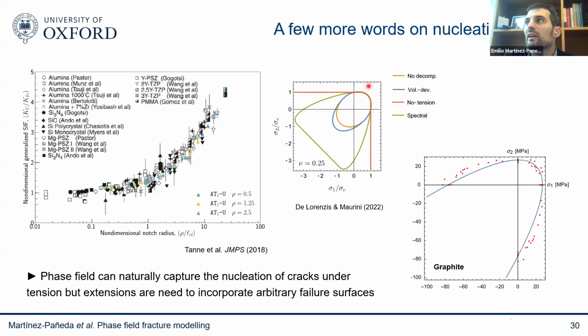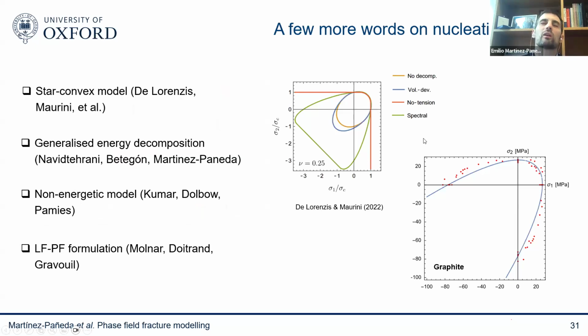With the no-tension split, that is quite used for masonry materials, you get something like this, and also the spectral split. But there are many others, and there's a lot of people working on trying to incorporate any arbitrary failure surface. So you say, now I'm working with granite, with cast iron, with this type of rock. Okay, we have these experimental data points. Let's feed that to a failure locus and bring that failure locus into phase field. So this is very much an ongoing area of work. And just to cite a few people, the group of Laura De Lorenzis at ETH, they're working on their star-convex model.